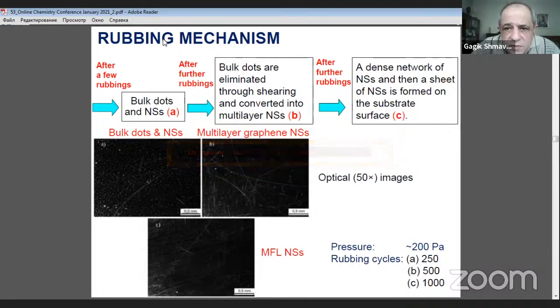So, okay, let's see the optical images of this. After a few rubbings, bulk dots and nanostrips appear. After further rubbings, bulk dots are eliminated through shearing and converted into multi-layer nanostripes. After further rubbings, a dense network of nanostripes and then a sheet of nanostripe is formed on the substrate surface. And you can see below the conditions of the rubbing, I mean the pressure and the rubbing cycles.